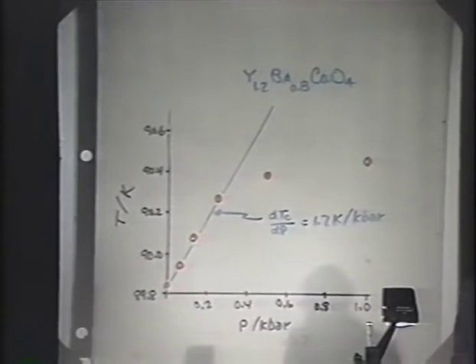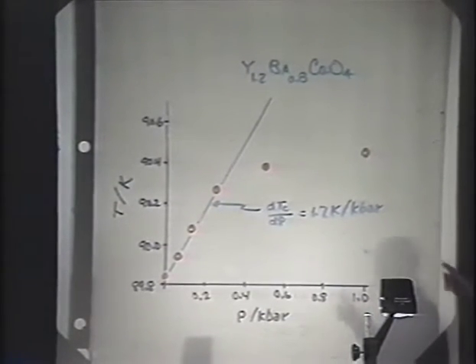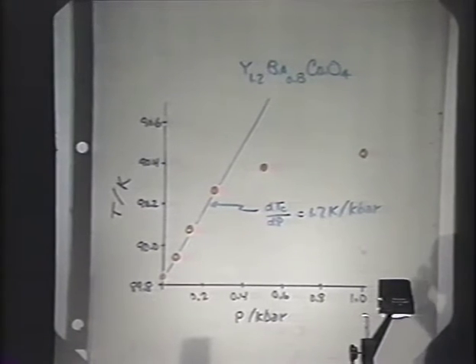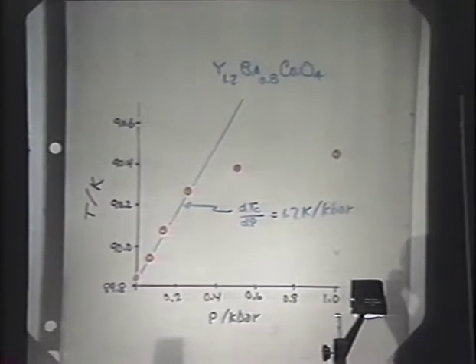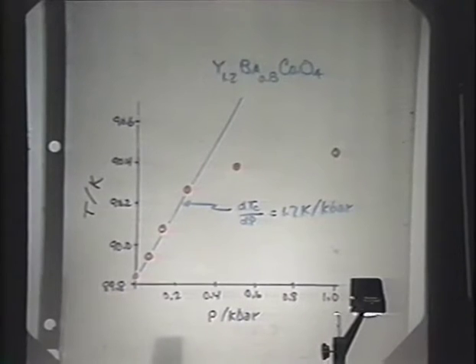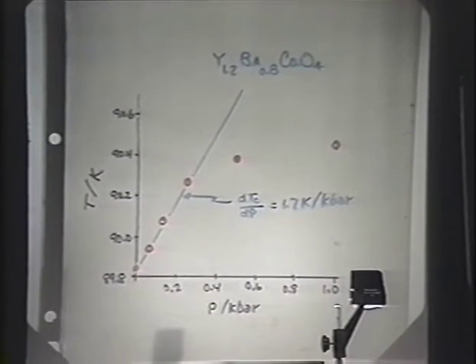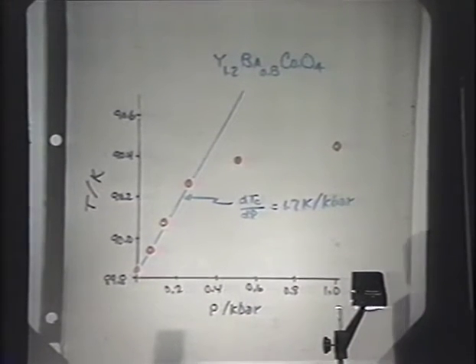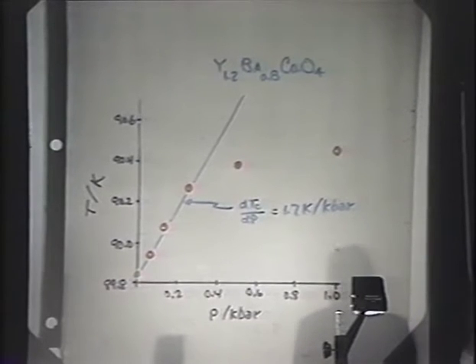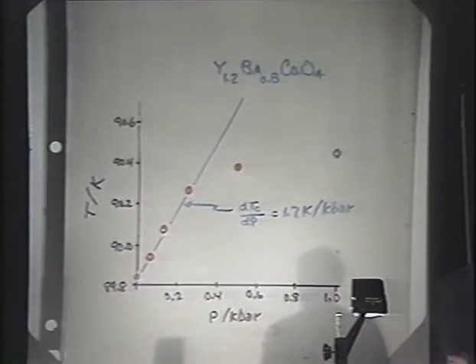If we blow this up and look in the first kilobar, we see this is the same data just stretched out, that we have, as I indicated, about 2 degrees per kilobar, and then going to less than 1/10 of a degree. A factor of nearly 30 change in the apparent compressibility.